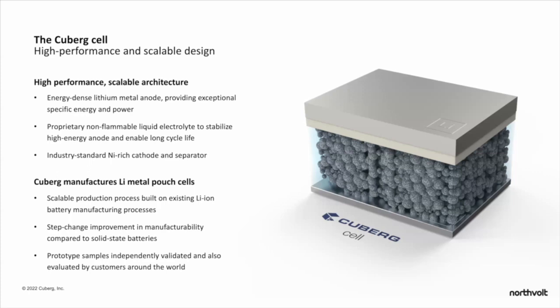To make lithium metal work, because it's a very sensitive and reactive material, we have developed a new non-flammable liquid electrolyte to stabilize this anode and enable good cyclability and reliability. This is in contrast to a lot of companies these days that are developing solid-state electrolytes, where instead of using a liquid, they've really changed completely the architecture of the cell to use a solid membrane as the separator and the electrolyte for ion transport.